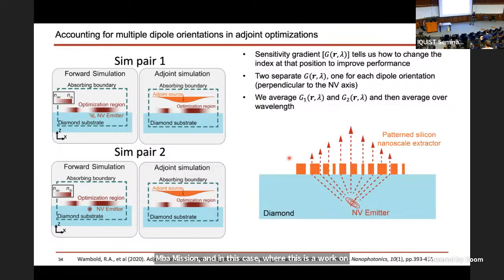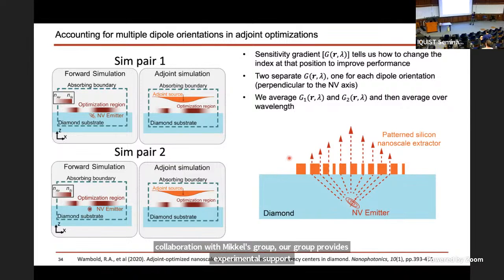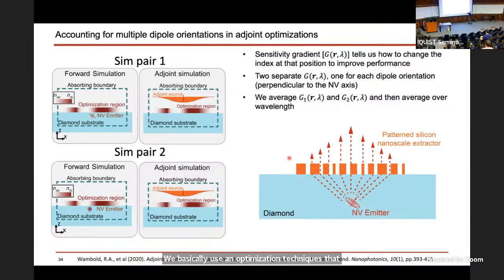We basically use adjoint optimization techniques that optimize for extraction of light from both polarizations, both of these X and Y dipoles, in order to better extract light. So our structure consists of a thin layer of silicon on top of diamond. The nice thing about this approach is that you avoid etching the diamond surface, again so that you're not degrading the near surface spins.